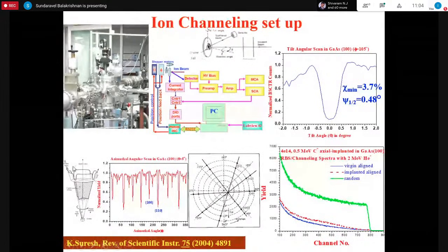And by tilting it, when we rotate, whenever you come across some plane, you see reduced yield, and we get many dips, something like this red color curve. This gallium arsenide is a zinc blende structure. In this one, it has a much lower chi minimum. So 110 is deeper, and the shallower one is 100. Once you scan with respect to the axis, like in this left hand schematic, you'll be getting different peaks.